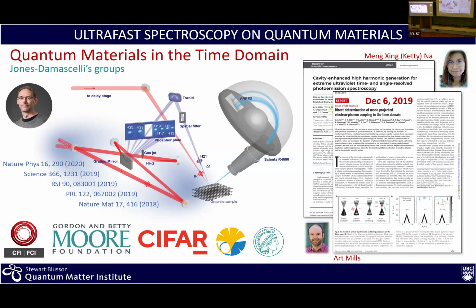And this is done based on a technique which is basically a passive enhancement cavity. It's a way of doing high repetition rate generation of photons with very low peak powers. And then you go select the particular harmonics you want to have. And at the same time, you have now an infrared beam that comes in, and the two of them you can control with a delay, so that you can see what happens and take a movie of your electron excitations in the material.